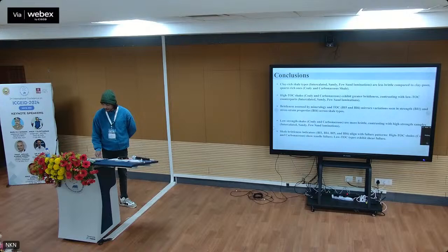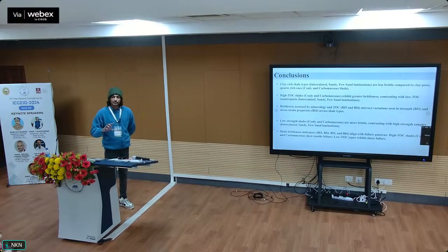Low strength shells are more brittle, contrasting with high strength shell samples. So even though I told you that UCS and tensile strength ratio gives us brittleness index, so higher UCS should give us more brittleness. But in our results, low strength shells are giving more brittleness because the ratio would depend upon the type of rock type we are using. For example, if you are comparing Kohli shell and silty shell, in that case silty shell would have more strength, but it would also have more percentage of clay minerals. So that would also affect.